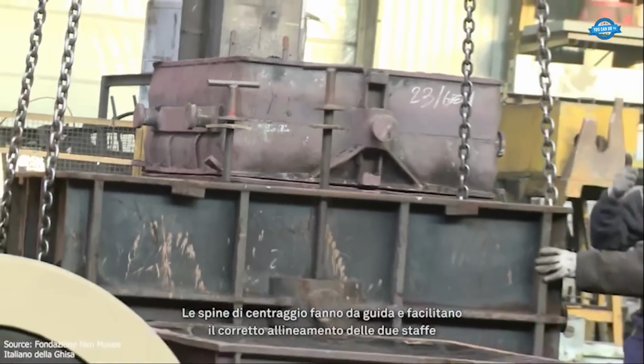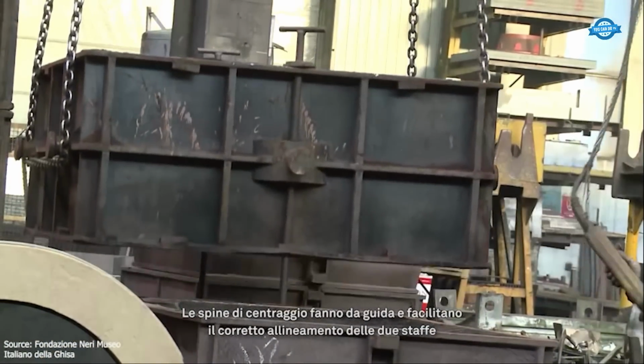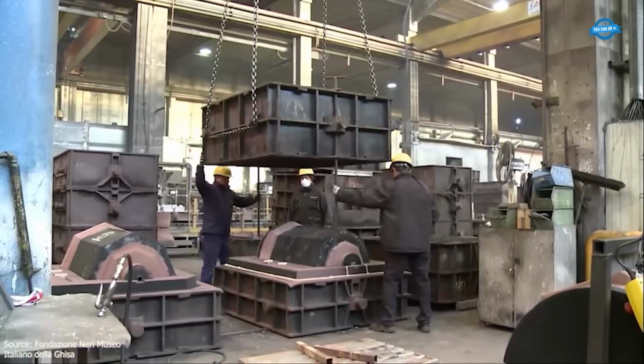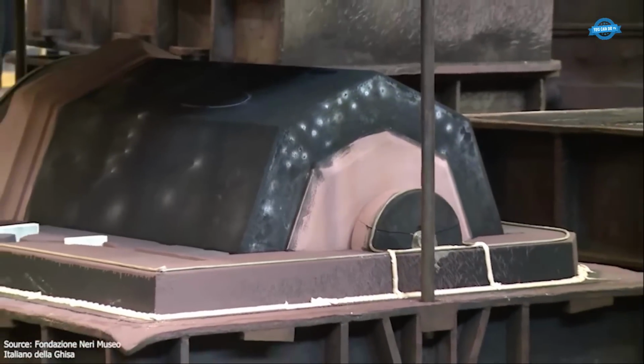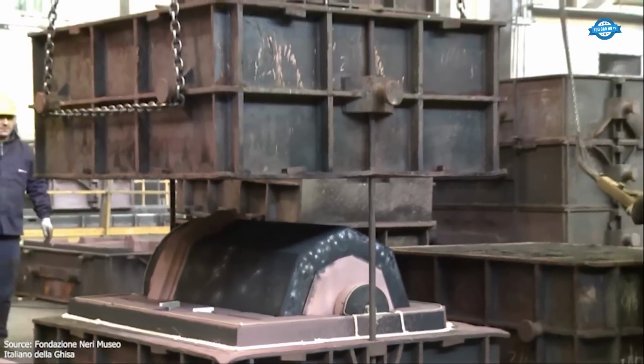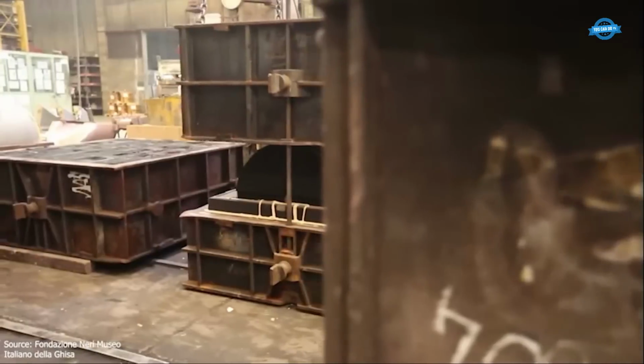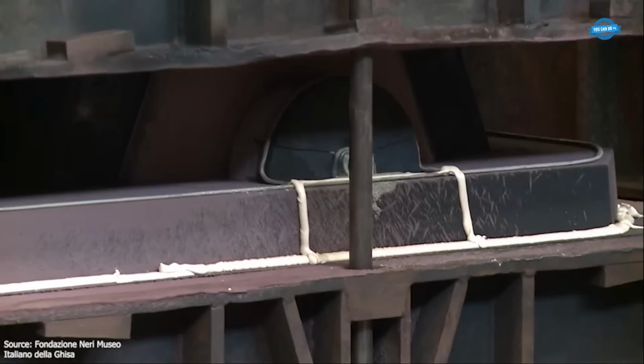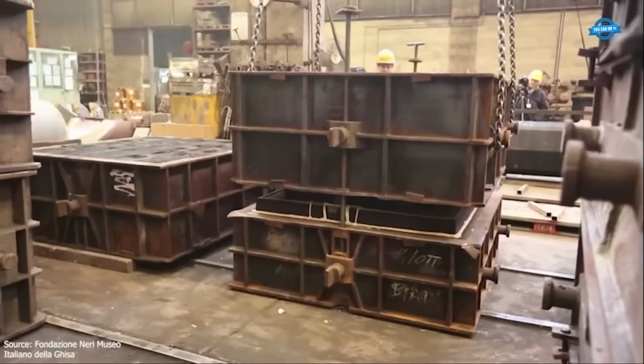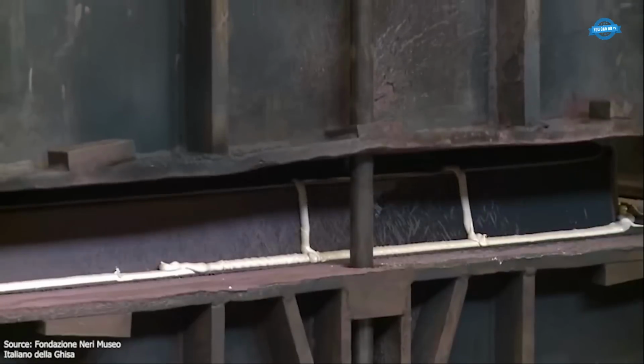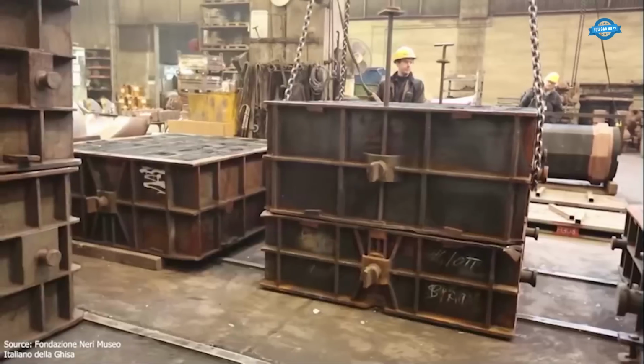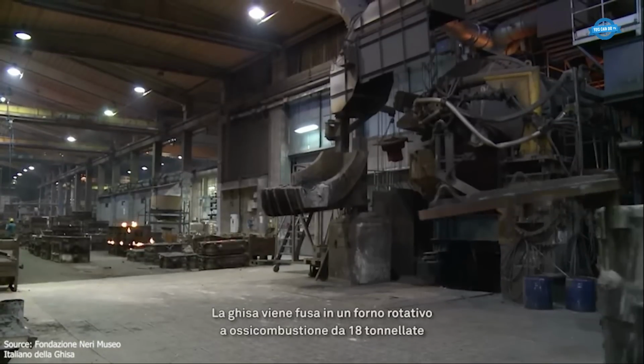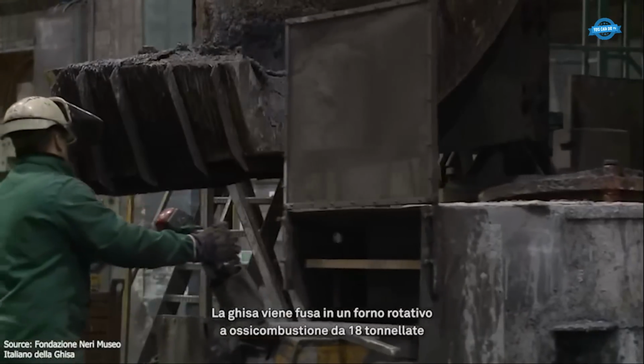Meanwhile, cast iron is melted in an 18-ton oxy-combustion rotary furnace. The process of melting the metal to reach the required temperature of 1,500 degrees Celsius takes approximately 2 hours. During melting, impurities rise to the surface as slag and are skimmed off to improve the purity of the molten metal. A temperature probe is used to ensure that the iron reaches and maintains the optimal pouring temperature.